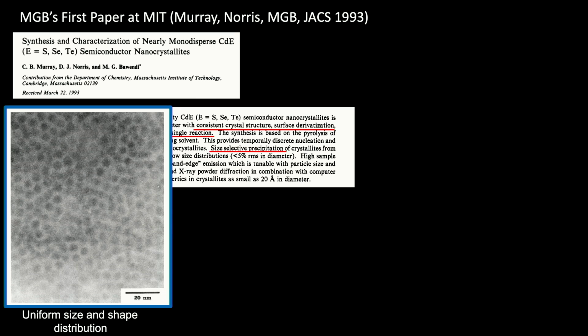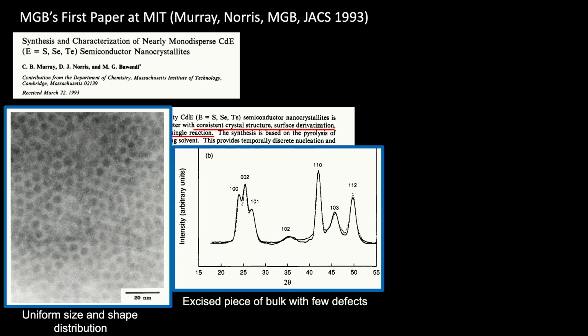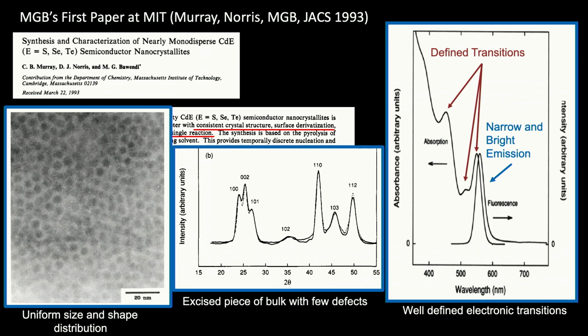You can see they're basically all the same size from that paper. The dotted line is the crystal X-ray, powder X-ray. The solid line is a model of what an X-sized piece of the bulk would look like if you just take it out. And the line width corresponds to the size of the particle. So it's a true piece of the bulk with very few defects. Now we can see the harmonics in the absorption. So there's the fundamental, and these are the waves that have more waves than one cycle, basically, of the electron in the box. And the emission is nice and fairly bright.